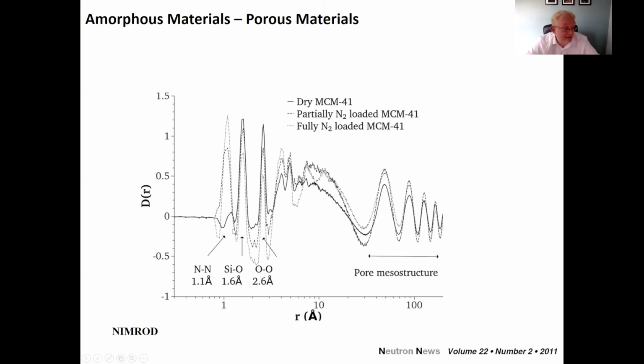And there's some change in the silicon-oxygen distance, but it is mostly relative to the total scattering within the system, and there is no real change in the position of this peak, which means that the material is not bowing or buckling under nitrogen loading. So we're not actually causing it to swell or change in volume.